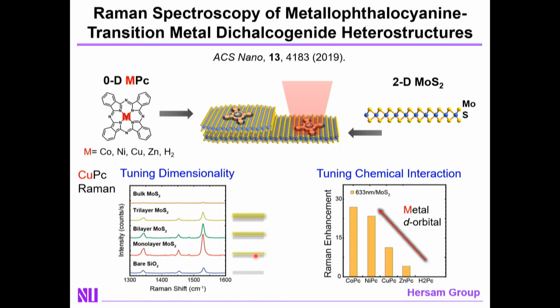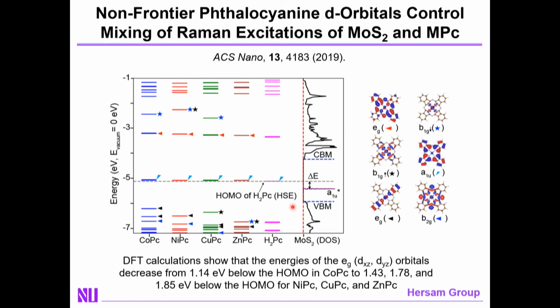Now, interestingly, as you look at this Raman enhancement as a function of the metallo-phthalocyanine's metal atom identity, you see a very clear trend, which appears to depend upon the metal d orbital. I will note that the d orbitals are not the frontier molecular orbitals, so this is not just explained by the HOMO-LUMO gap, but instead, if you look carefully at the d orbitals, which are the non-frontier orbitals, you see a correlation between their energetic position and the degree of Raman enhancement. The point of this slide is to note that it's not just HOMO-LUMO that matter in the zero-dimensional side of the mixed-dimensional heterojunction, but also the non-frontier orbitals, giving you further tunability over the possible properties that could be realized.